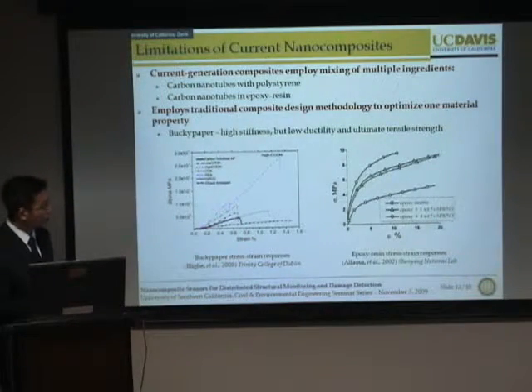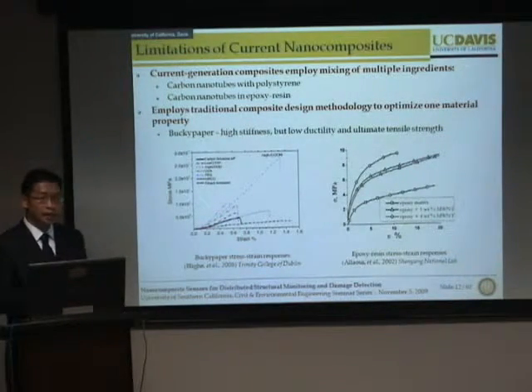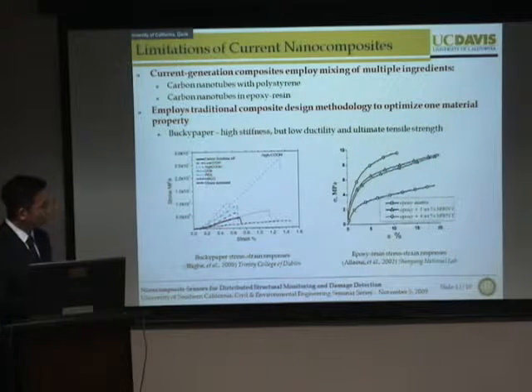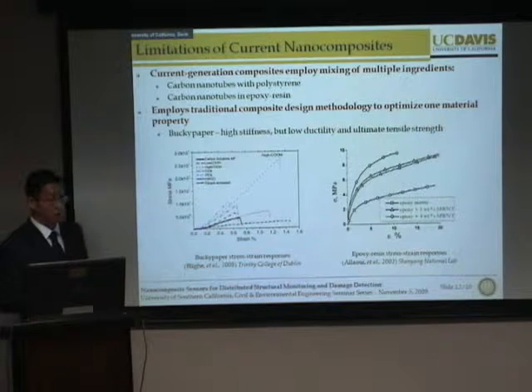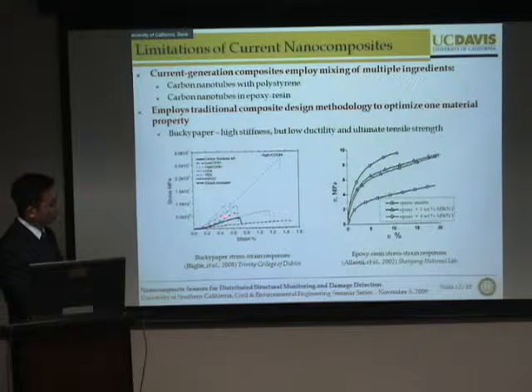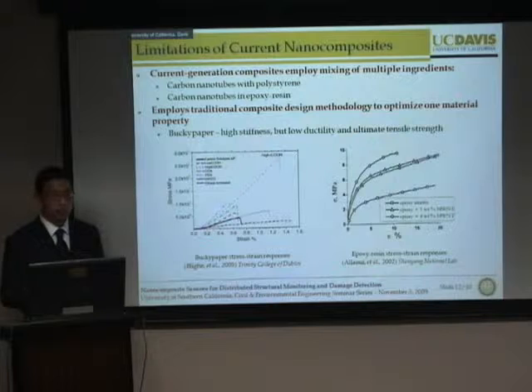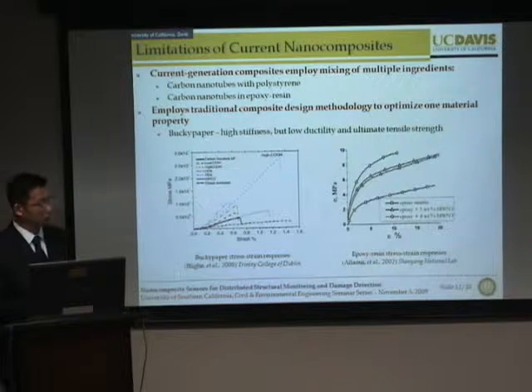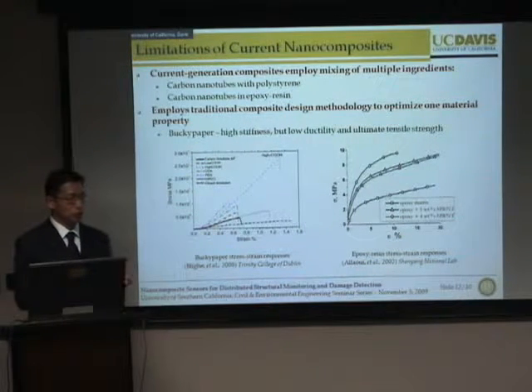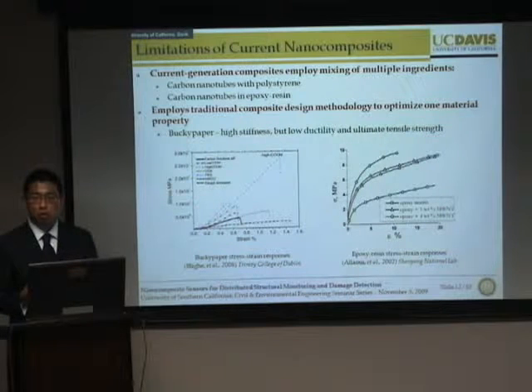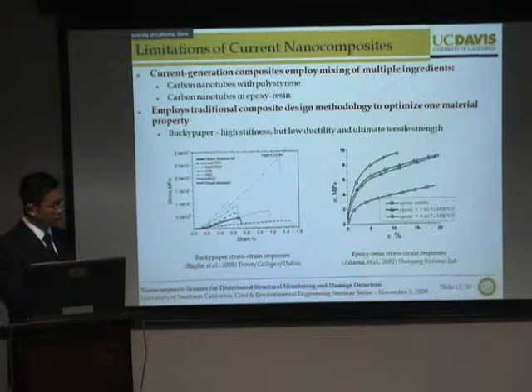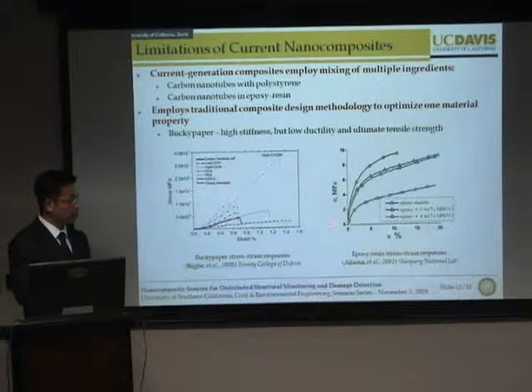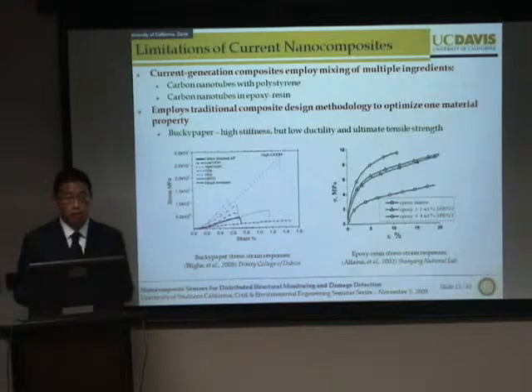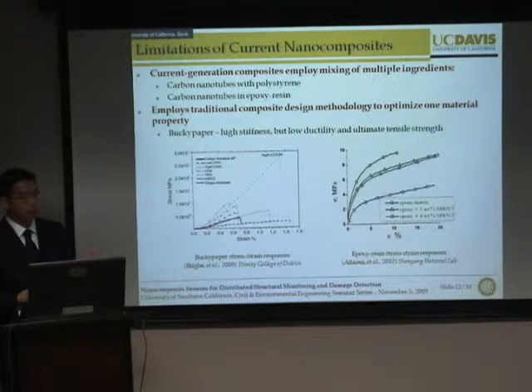Now, if we look at some of the recent results looking at the mechanical performance of these thin film composites, we can see that although Bucky paper specimens exhibit linear stress-strain behavior, the material itself is in fact quite brittle, fracturing at 600 to about 1,400 microstrains. But if we can put this carbon nanotube material in a more flexible matrix, like an epoxy, we certainly get a very flexible material. But the problem is that the material behavior is highly nonlinear.